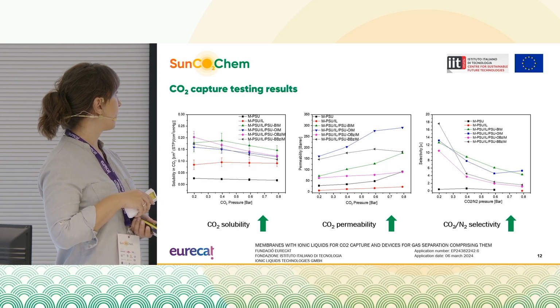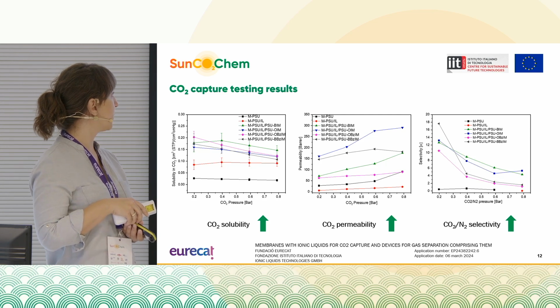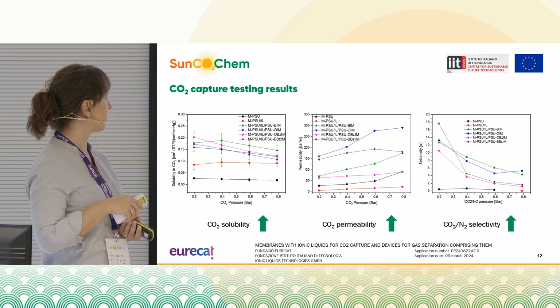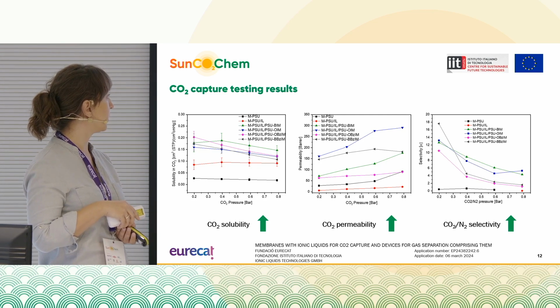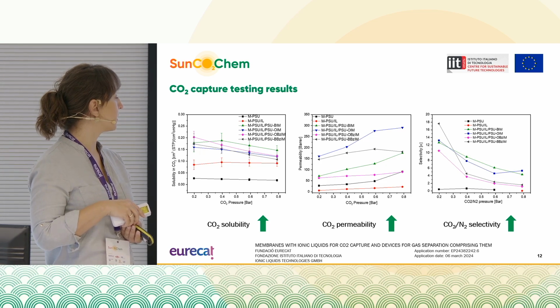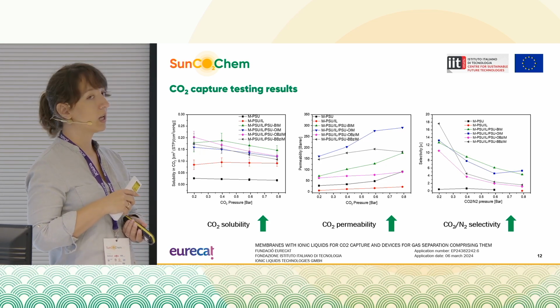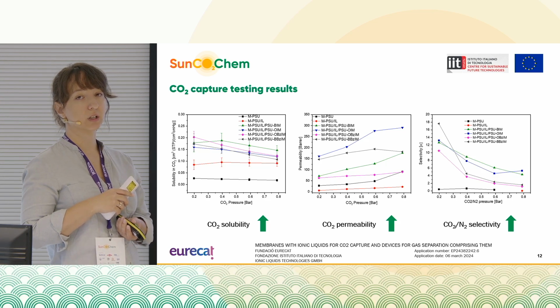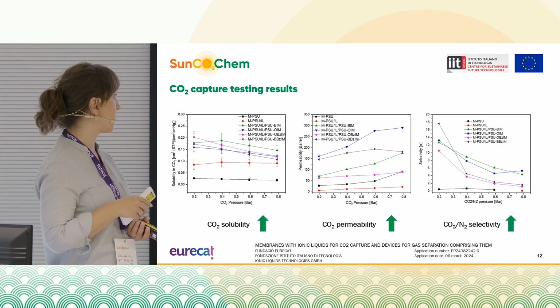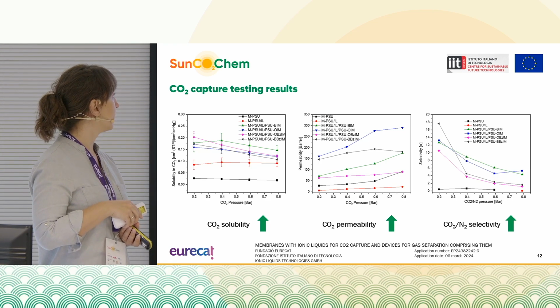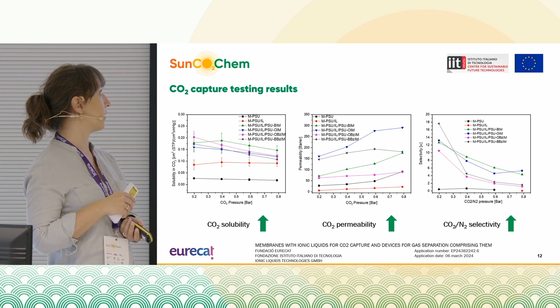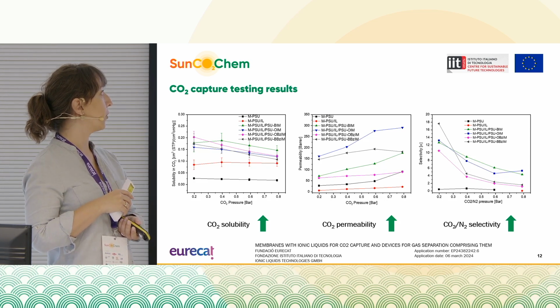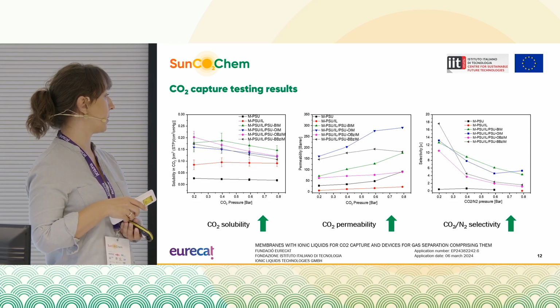In the case of the permeability measurements, we saw that the simple incorporation physically of ionic liquids slightly decreased the permeability in comparison to a blank polysulfone membrane, which is probably connected to increased thickness of the membrane. However, again, each further addition of the modified polymer increased the permeability.